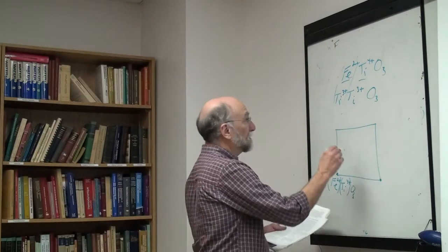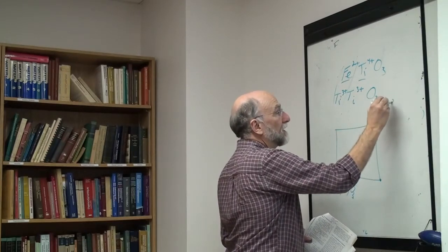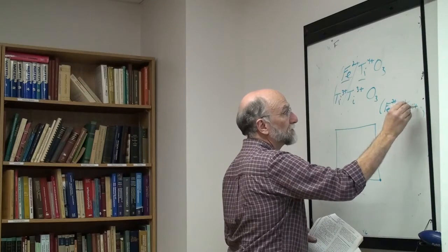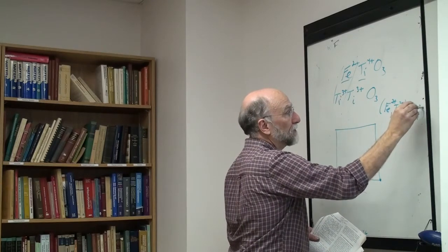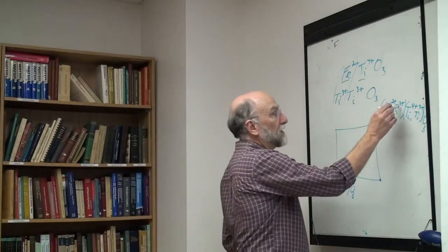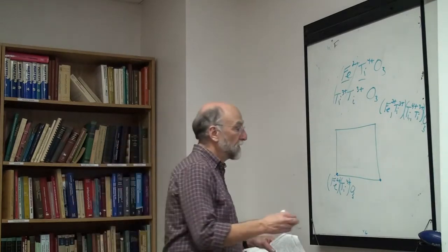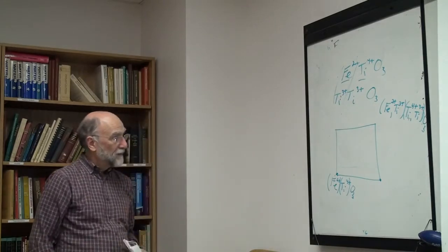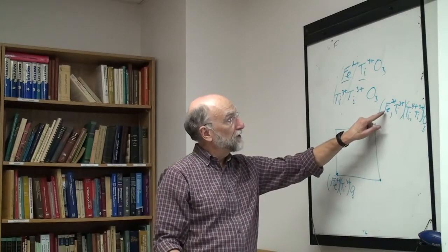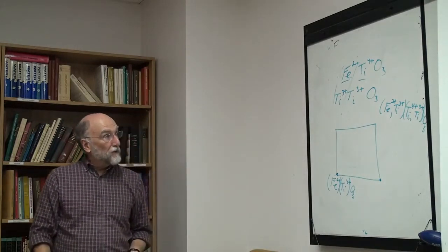Over here, we're going to model it as Fe2+ Ti4+ on one sublattice, and Ti4+ Ti3+ on the other, with O3. So in this sublattice you can get iron and titanium 3, and in this sublattice you can get titanium 4 and titanium 3. Doing it that way, we have our 4 compounds. One compound is iron titanium 4, the next compound is iron titanium 3. Every pair of atoms in the 2 sites gives you an end member.